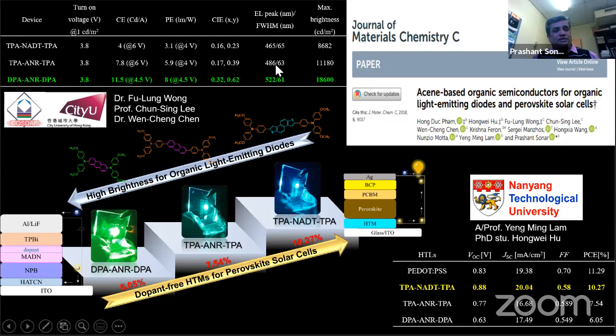The OLED data is really not that bad. Getting a brightness of 18,600 candela per square meter is quite high. And then look at the turn-on voltage, which is 3.8, a very low turn-on voltage. We also get a very narrow peak, FWHM meaning full width at half maximum, so we get a nice narrow emission. And our emission can really be tuned based on these backbones.